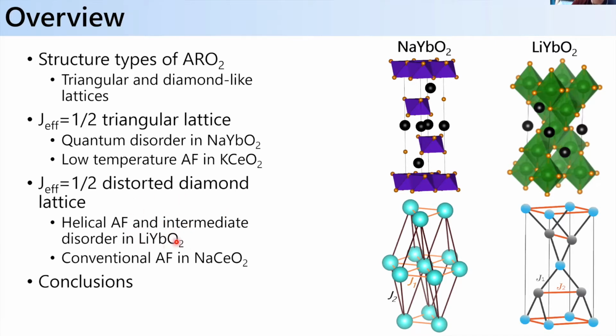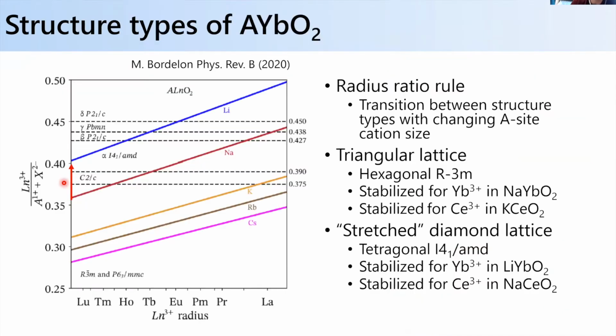We'll take a look at the ytterbium variant, which is the single hole variant, and the cerium variant, which is the single electron variant. And I'll explain in the next slide what we mean by J effective 1/2 and what I mean by single hole and single electron magnetic ions in these systems. But first, before I do that, I just want to show you this nice empirical, what they call radius ratio rule, which determines which structure type is selected as you take the chemical formula ARO2, or more generally ARX2, where X in this case is the chalcogen ion, R is the lanthanide ion, and A is the alkali ion.